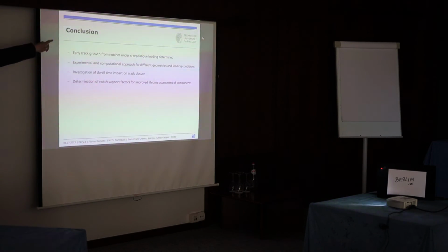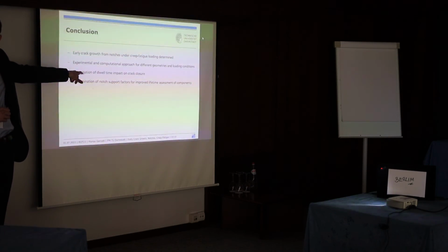So we were more focused on the global force displacement curves to determine this energy difference. And I looked in detail at the stresses along the crack path during the dwell times. I didn't show it today here, but there we clearly see a relaxation during the dwell times because we're in strain controlled conditions. So if we have this dwell time in compression, the stresses along the ligament relax, and as well the stresses along the crack flank relax. So if we then apply a load again, you don't need much load, and the crack is already open. So that's why the crack tip loading increased.